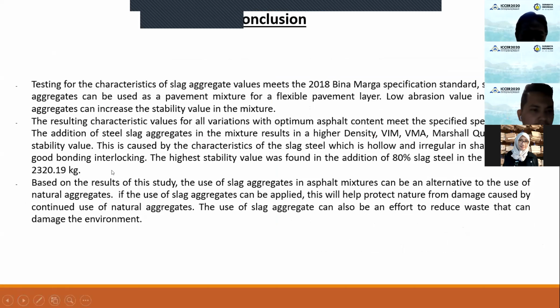Conclusion: testing for the characteristics of steel slag aggregate values meets the 2018 Bina Marga specification standard, so that slag aggregate can be used as a pavement mixture for flexible pavement layer. The low abrasion value in steel slag aggregate can increase the stability value in the mixture. The resulting characteristic values for all variations with optimum asphalt content meet the specification.